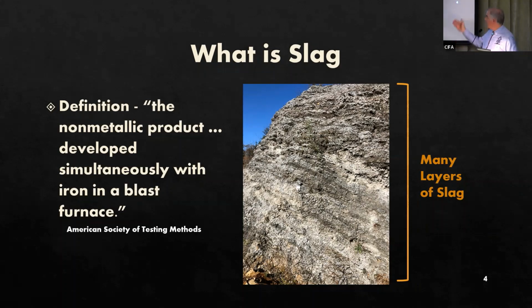The photo on this slide, which you see, shows about 40 to 60 layers of slag that accumulated over time. Some of you might be familiar with this. This is pretty close to Cornwall Manor. If the slag was deposited in this location twice a day, you're looking at about 1 month's worth of slag that accumulated at this location in this 20-foot thick section of slag.